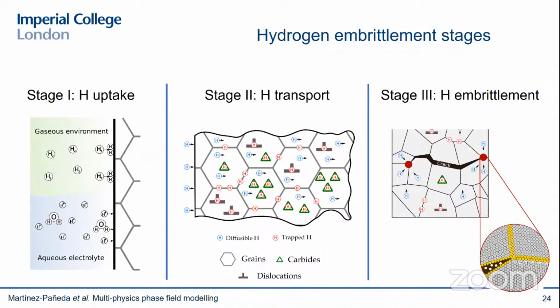And to me, the key to prediction is that you need to be mechanistic. You need to be able to resolve the physical processes that are governing all the stages involved in hydrogen embrittlement. From the uptake of hydrogen, the ingress of hydrogen into the metal, to the transport of hydrogen through the crystal lattice, to the embrittlement process itself. So the accumulation of hydrogen in critical interfaces and the nucleation and growth of cracks as a result of that.